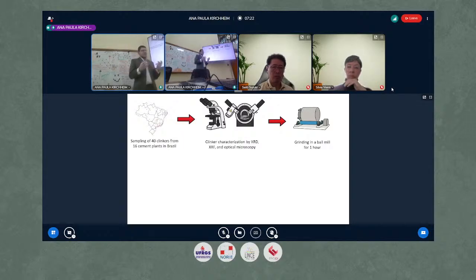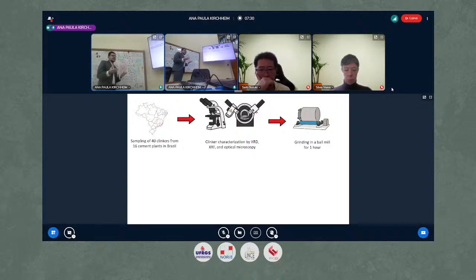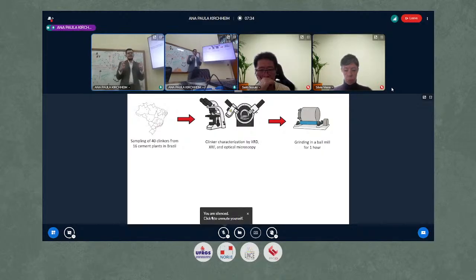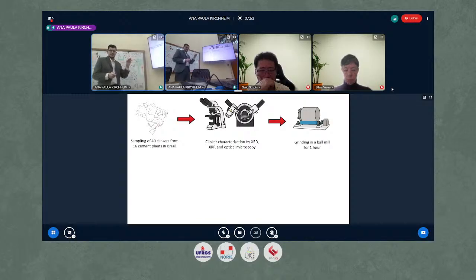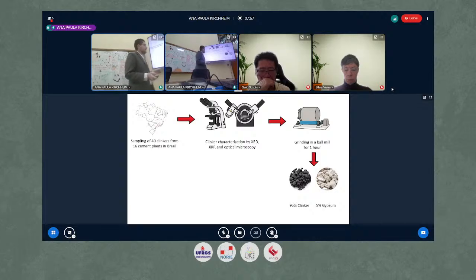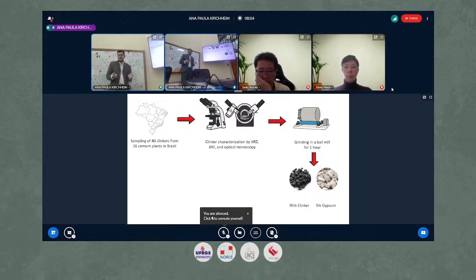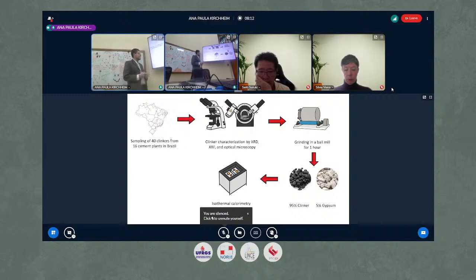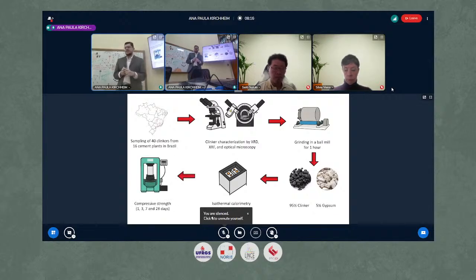Obviously, we will obtain clinkers with different particle size distributions that will affect the reactivity. But the idea here was to evaluate how the grindability, how hard it is to grind the clinker, will affect its properties. Because a clinker harder to grind means more energy and more resources to grind. So all the clinkers were ground by the same mill and time. We didn't optimize the sulfate content here. We used 95% of clinker and 5% of gypsum, due to material limitation. Then we ran isothermal calorimetry up to 7 days and compressive strength at 1, 3, 7, and 28 days.